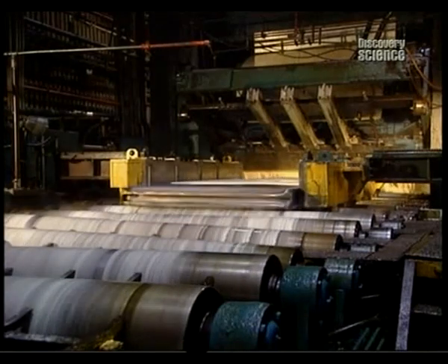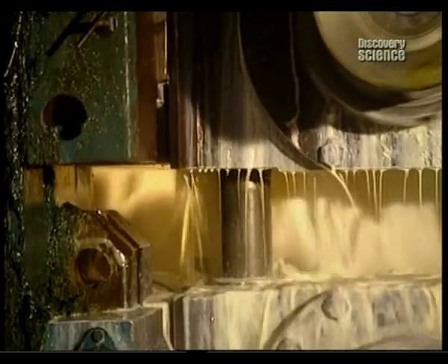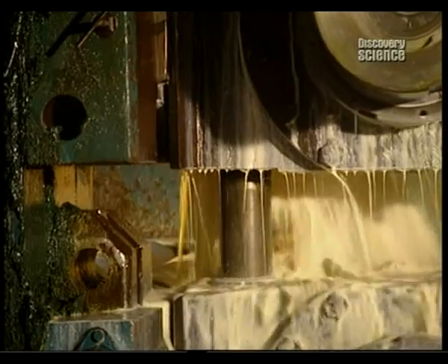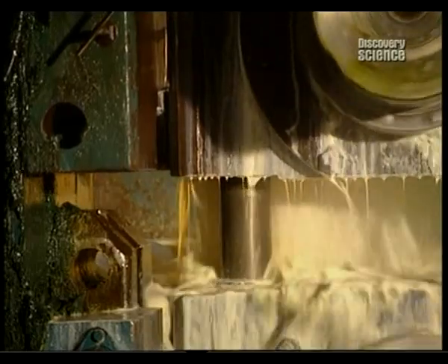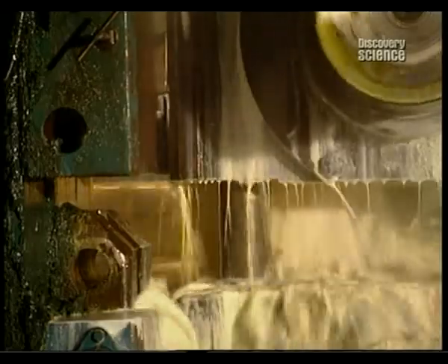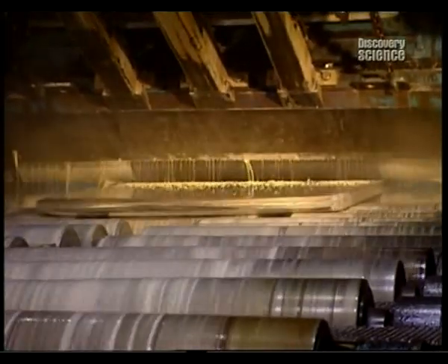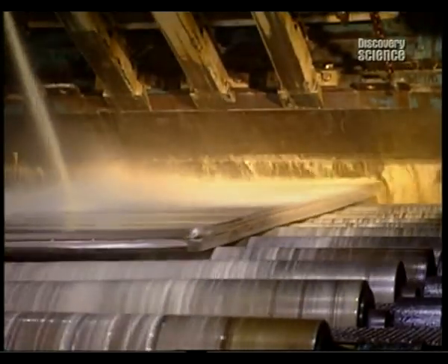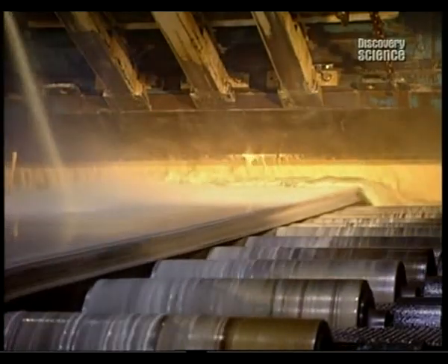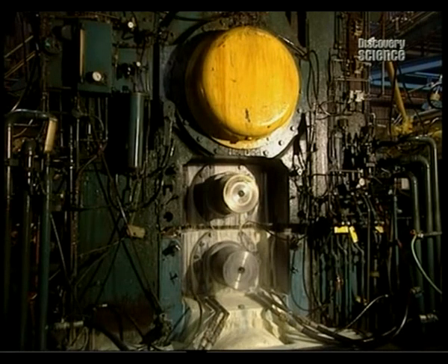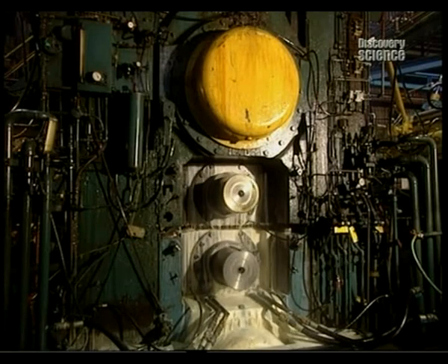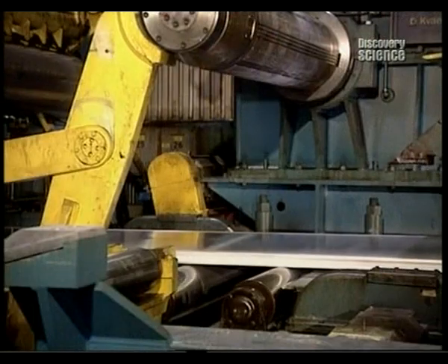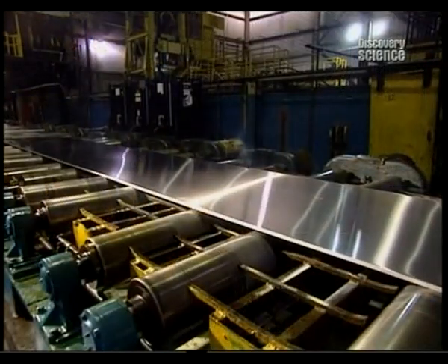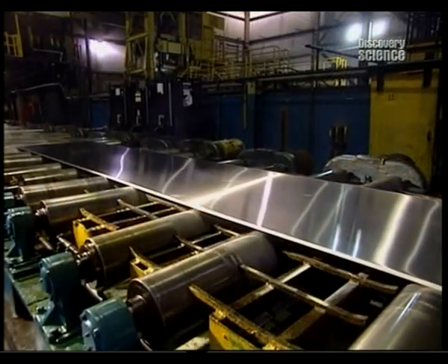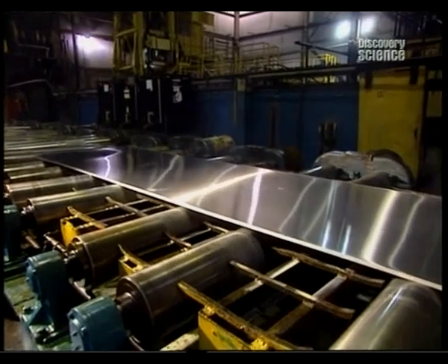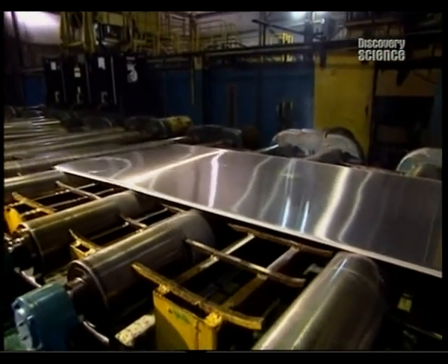Starting from a thickness of 45 centimeters, the ingot becomes increasingly thinner with each pass-through. The aluminium slab may have to pass through the crushing rollers 16 times before the right thickness can be achieved. The ingot now measures 7 centimeters in thickness, but still it has to get down to just half a centimeter. Now the ingot is 5 centimeters thick and measures over 9 meters in length. The plate takes its last journey over a conveyor to the final milling stages.